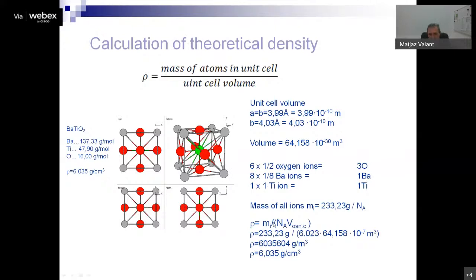Now we use the mass of the atoms that we can find in the periodic table and calculate the mass of all these atoms inside the unit cell. And when we divide these two numbers, we get the theoretical density. Now, this theoretical density is useful when we, for instance, produce barium titanate ceramics. We can measure the density of the ceramics, compare it to the theoretically calculated density, and then we understand how dense this ceramic is. Is it perfectly dense without any pores inside, or does it contain some pores?